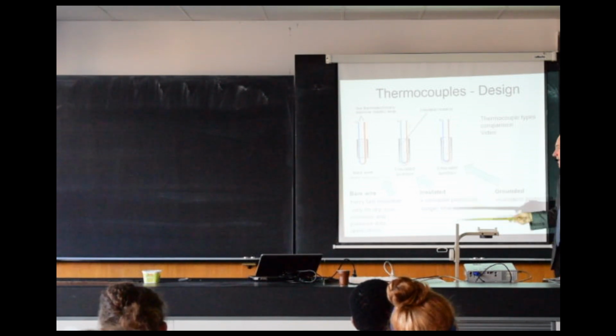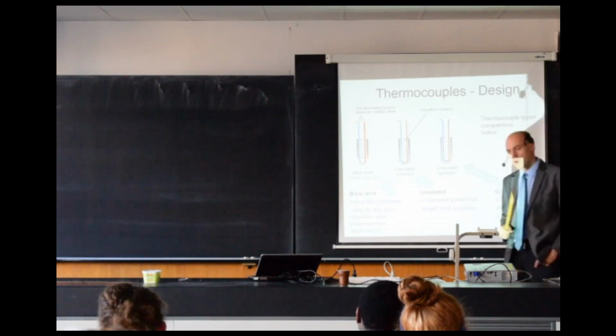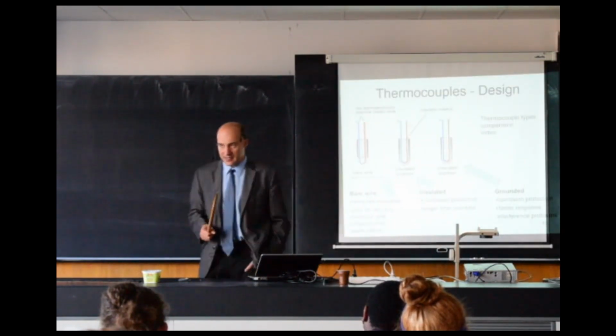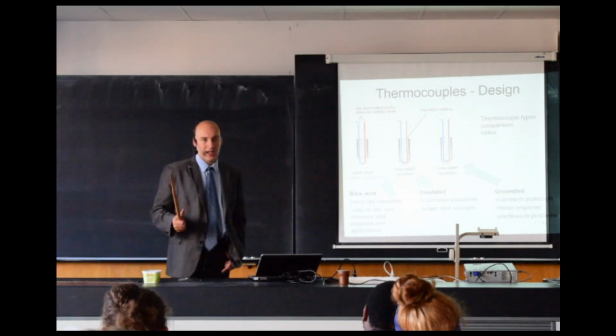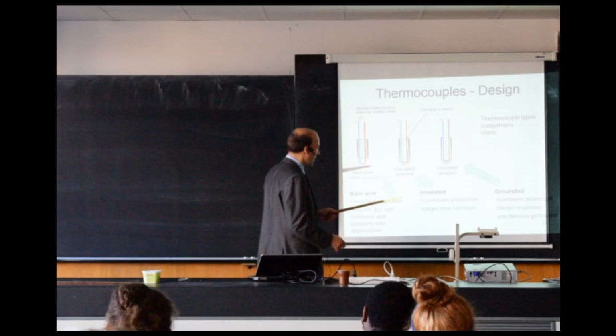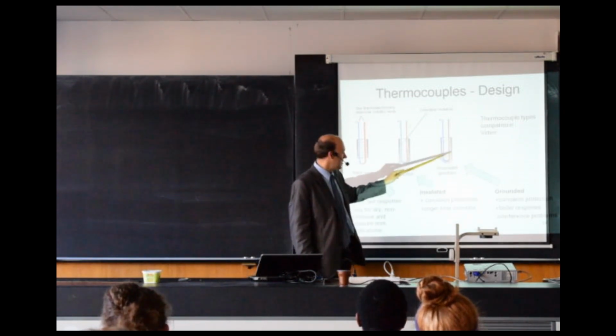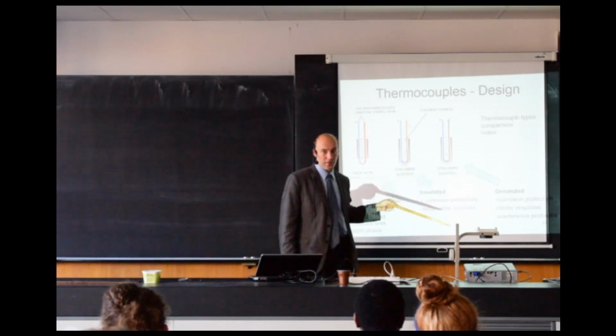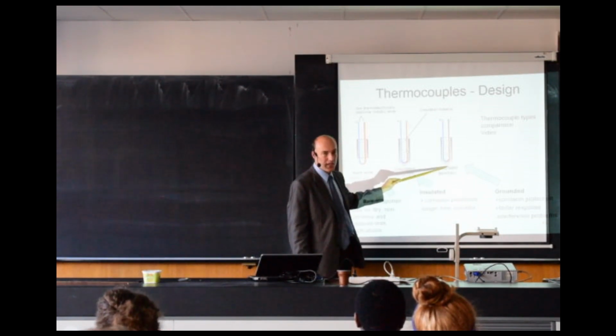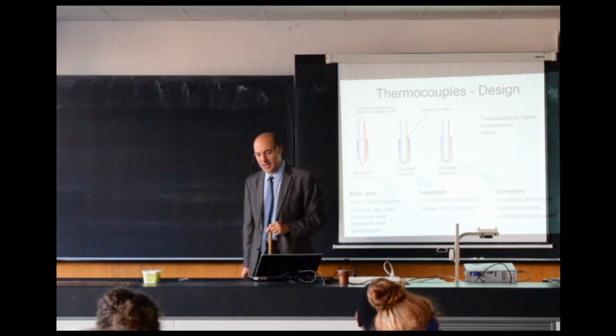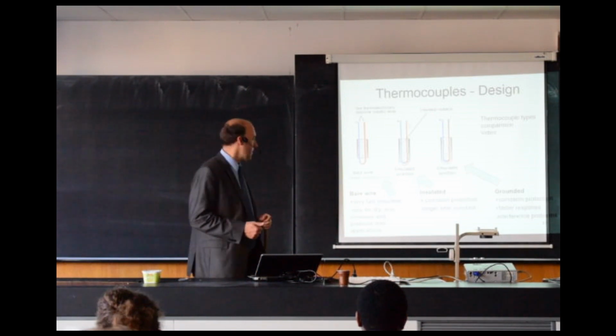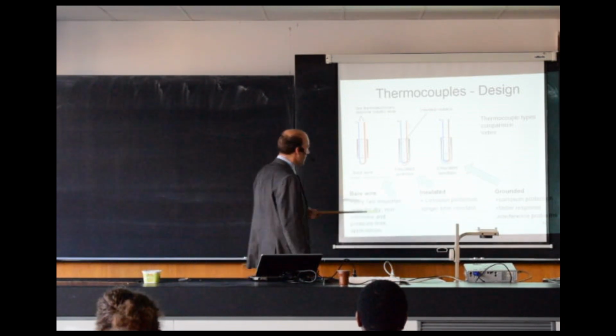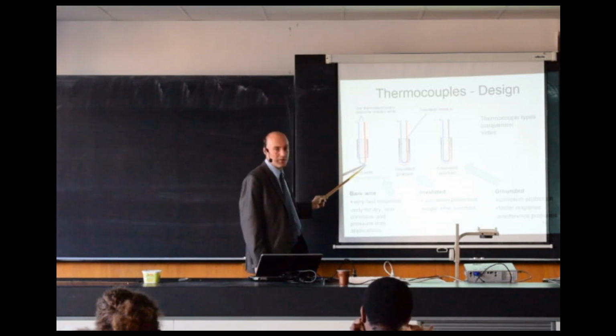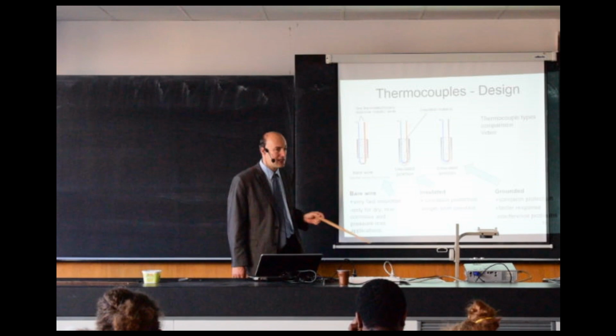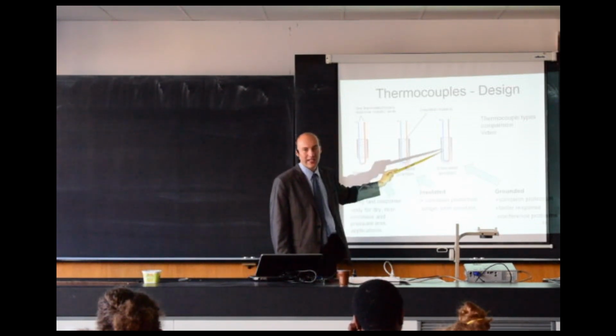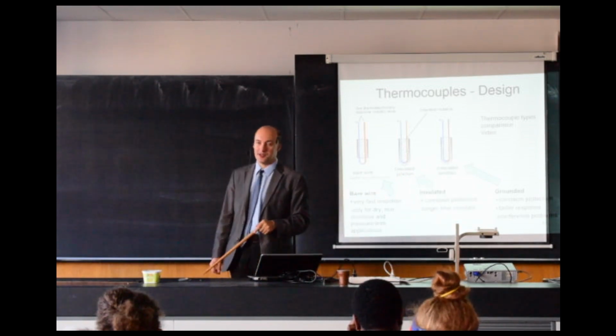Somewhere in between is this third option. This is called a ground junction, and somewhere in between means that it has good corrosion protection, since it is protected by the thermal well. It has a faster response because the thermocouple is directly welded into the end of the thermal well. So it has a good heat transfer, so it will have shorter time constant than the insulated connection, but definitely longer than the bare wire. But on the other hand, since this is a metallic sheet, it will act as an antenna, and you can have problems with electromagnetic interference.